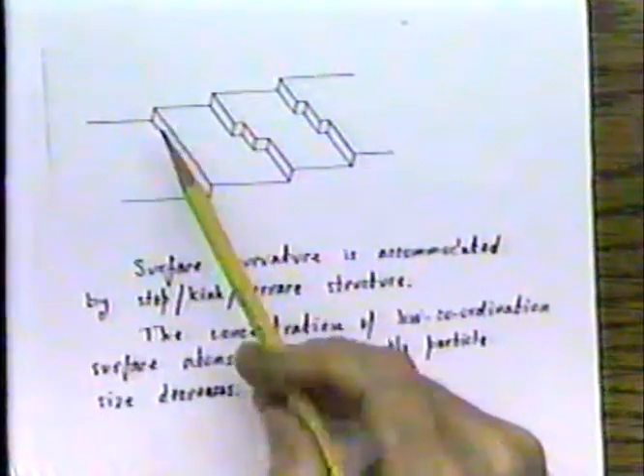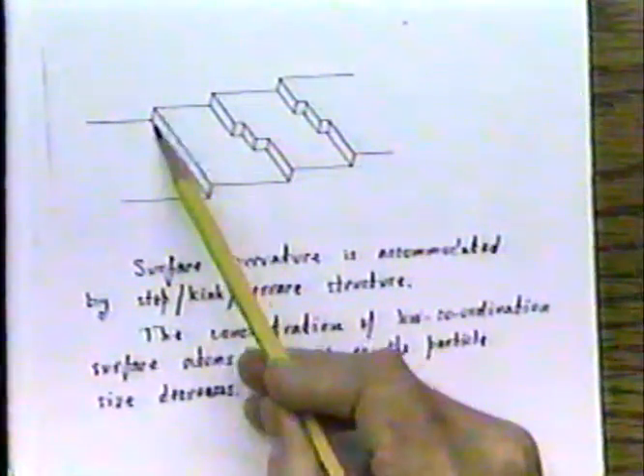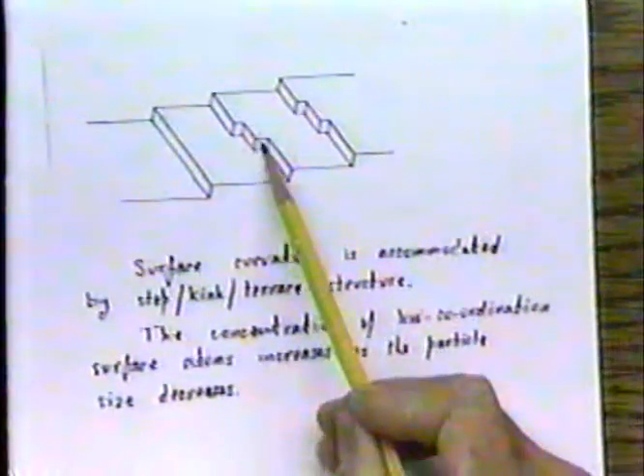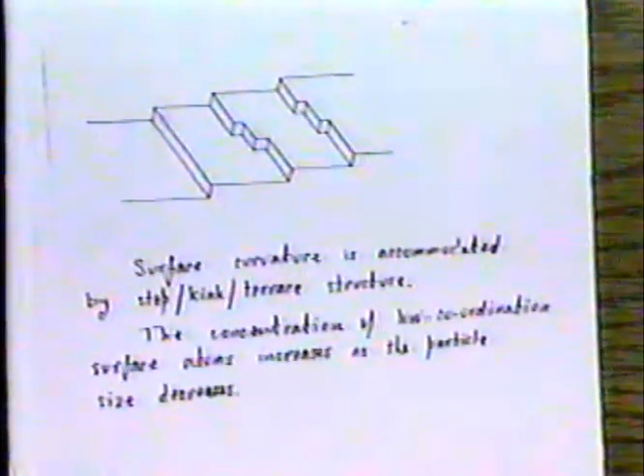And if you look at this, of course, you see immediately that an atom which is sitting in a corner position, and more particularly an atom which is sitting in a kink position, is rather similar in its low coordination to a corner atom in an ideal crystal. And this then is the origin of the statement I made a few minutes ago, that practical catalysts which have quasi-spherical metallic particles in them have an abnormally large proportion of surface atoms in those particles that are of a very low degree of coordination, and which therefore might be expected, if one can choose the reaction correctly, to have high reactivity.